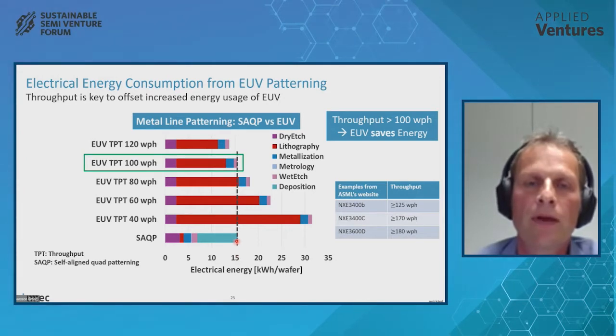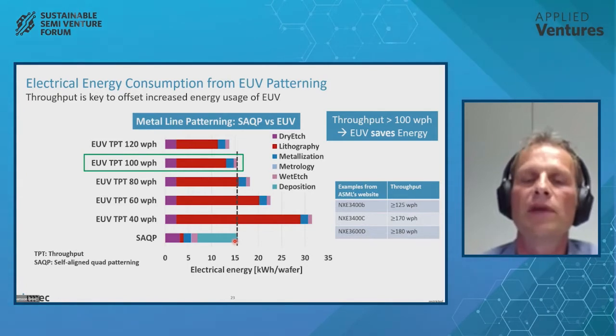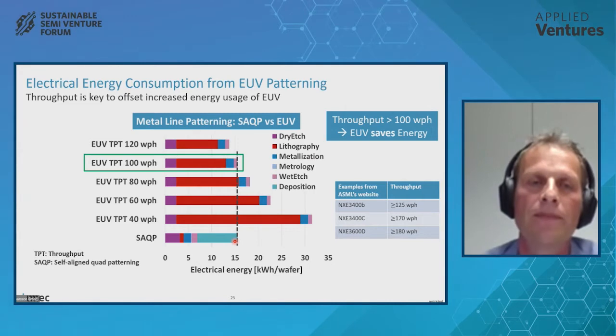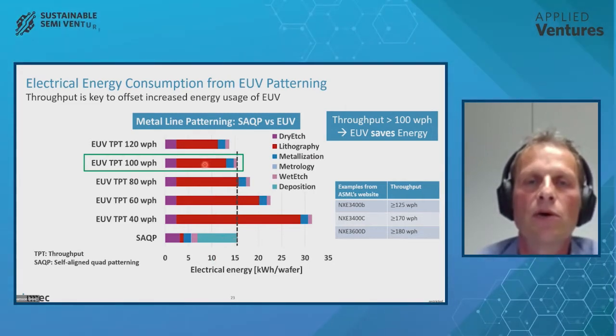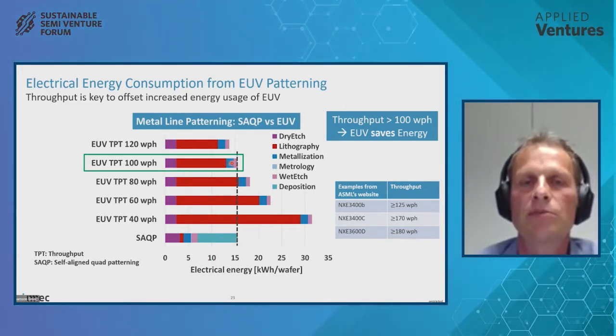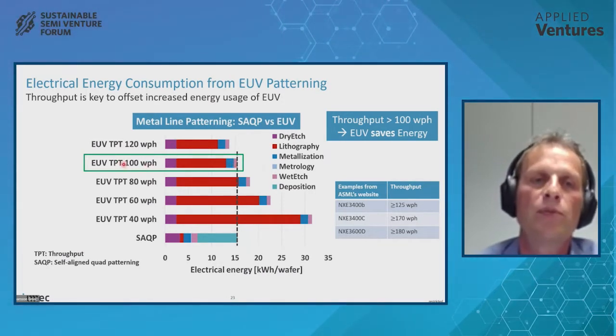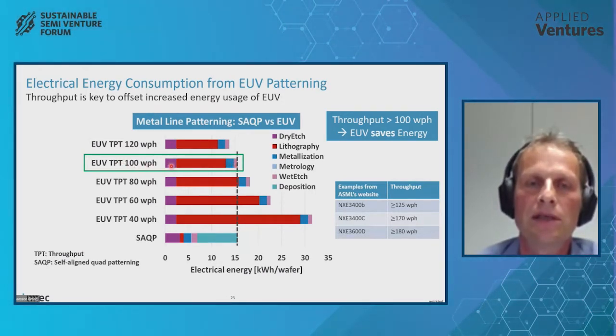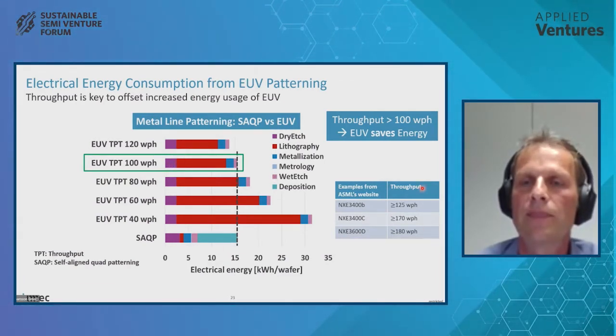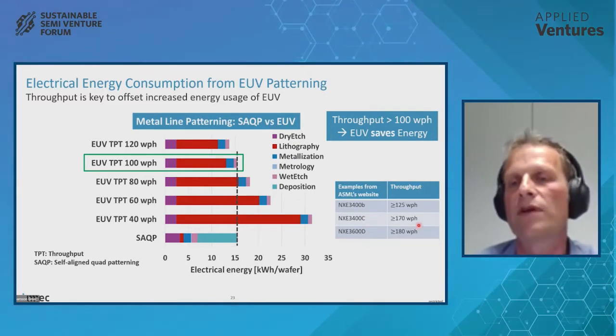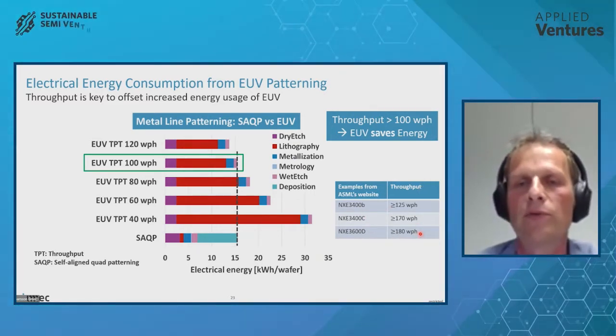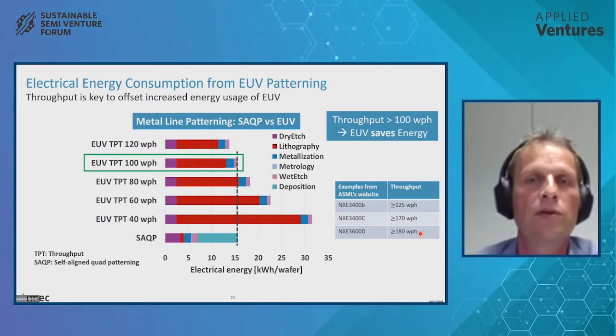You see here that deposition is really dominating, and that's because you need to deposit a lot of layers and then etch and then print and then deposit and etch and print and so forth. Whereas in the EUV case, the lithography is dominating and the rest is much, much smaller. So if your throughput is over 100 wafers per hour in this comparison, it's clear that EUV is actually better. And if you look at ASML's most advanced tools, it's very clear that the throughput is beyond 100 wafers per hour. So this looks quite good. EUV seems to actually save energy rather than the other way around.